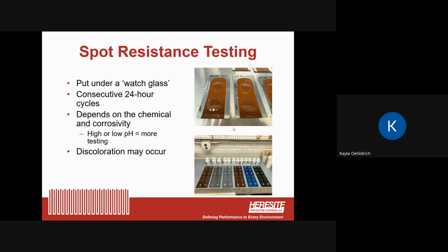We put it in for consecutive 24-hour cycles. So every 24 hours we inspect it and put the new chemical underneath it. That's done usually about 10 times consecutively, sometimes 8 times. It really depends on the chemical and how corrosive it is, whether it's a really high or low pH. It may require more testing. So it's important to note that discoloring may happen, especially with a phenolic. That doesn't necessarily mean, though, that the coating is not performing.